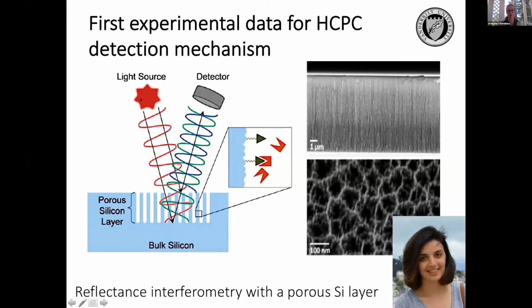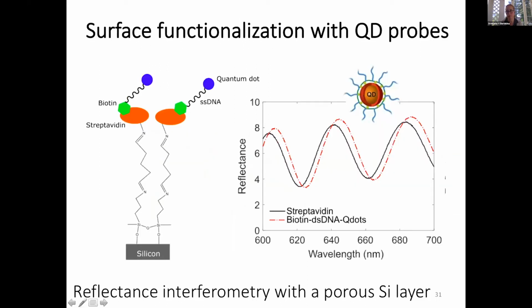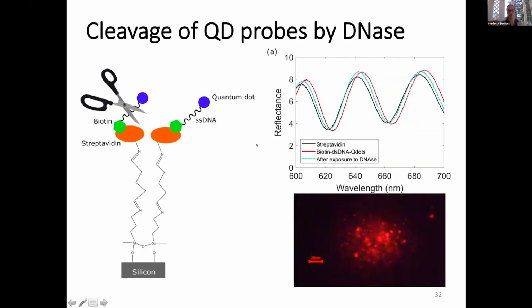So it works if you illuminate it, this one is interrogated vertically. So you come with the light, it bounces off, and you can measure the signal that emerges. And if you can attach or remove particles from the surface of this layer or from the volume of this layer, you can have a change in the signal. So we use the same functionalization technique. And as you add all this chemistry, there is a shift in the interference fringes. And as we add quantum dots, that shift is even larger. But as we cut them, the spectrum goes back almost to the original position.